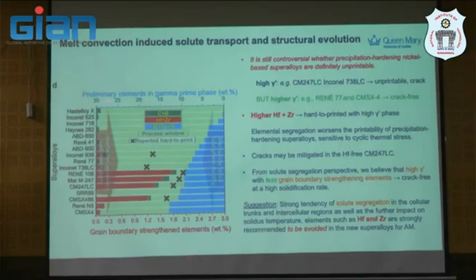representative nickel-based superalloys, based on the understanding that we said previously on the lower length scale model, we can see that the green one represents something that we can print, but the cross here, I mean this is a processing window, and the cross here indicates the hard-to-print alloys. You will see that most of the time they have very high grain boundary segregation, a strengthening element, and primary element for gamma prime. This is a systematic investigation now, but it's not all the time that you have some percentage of gamma prime and you cannot print them. What is said here means that not only one parameter can tell you. It's sometimes controversial because some high gamma prime alloys can be printable, or the processing window is wider.